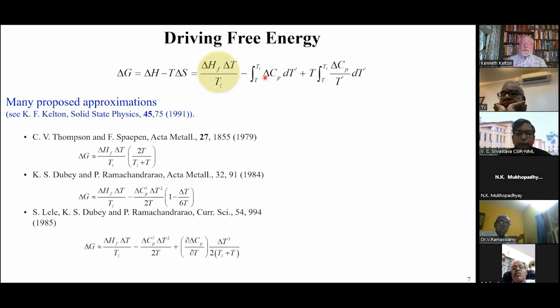But there have been many other proposed approximations, and I wrote an article many years ago where I looked at those. I just pick out three here. This is probably one of the most commonly used. It's Thompson and Spaepen in 1979. And the reason it's used is you don't really need anything other than the heat of fusion and liquidus temperature. You don't need to know anything about delta Cp.